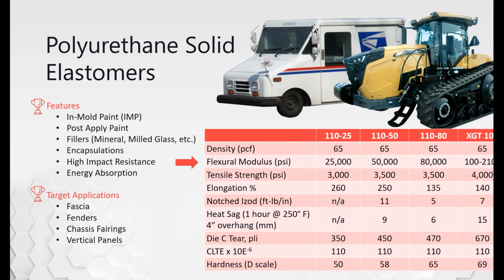Okay, gotcha. Let's talk about a little bit of the characteristics of solid elastomers. I love these charts. So this is a chart with some of the solid elastomers that we use, and you can see flex modulus or stiffness characteristics ranging anywhere from 25,000 psi up to over 200,000 psi. And actually, we have several others that we currently run that flex modulus is all the way down around 4,000 psi. So very, very flexible to pretty rigid, all capable in a solid elastomer.